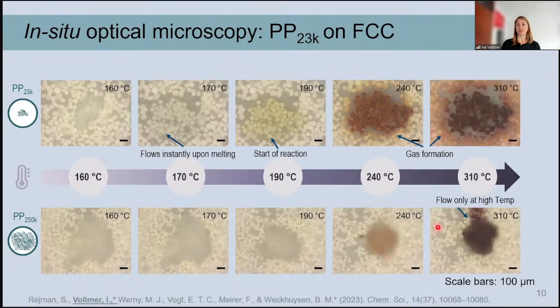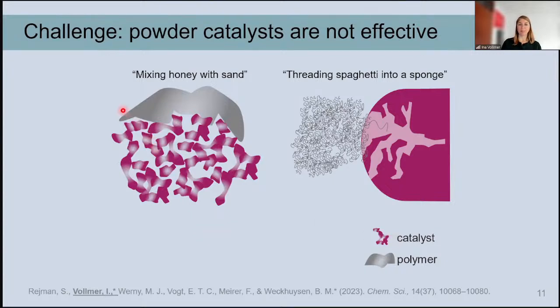And you see conversion at a much higher temperature than if you have this more low molecular weight polymer. And unfortunately, this polymer at the top, you can buy at Sigma Aldrich. But if you have a waste item, you will most likely encounter this bottom polymer with the high molecular weight. And so it's not very easy to contact the solid catalyst and the polymer particles. So getting the polymer into contact with the catalyst is as difficult as mixing honey with sand because the polymer becomes very viscous when molten.